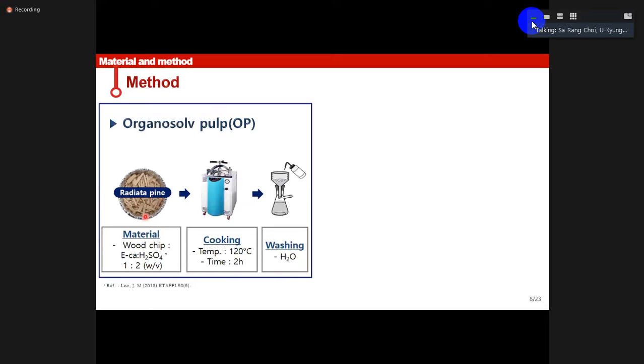This slide is about the experimental method. For making organosolv pulp as a raw material, the wood chips and solvent were reacted for 2 hours at 120 degrees Celsius in an autoclave. After the reaction, we washed lignin and solvent out with water to reach neutral pH. The yield of unbleached organosolv pulp was around 60%, and residual lignin content was 24%.